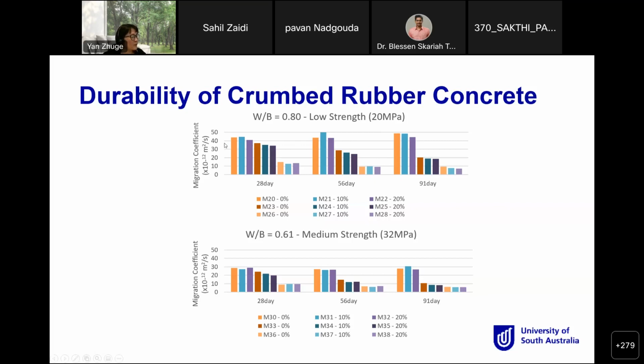So, for example, I look at 56 days. That is the normal mix without anything. So that is with 10% rubber. You can see the durability increased a little bit if you're just using normal Portland cement, but at 91 days it is slightly reduced. It's pretty consistent, but a little bit higher than the mix designs. For the 20% of rubber, actually you can see there's no difference at all, not much difference, even lower. So it's not a problem for chlorine.